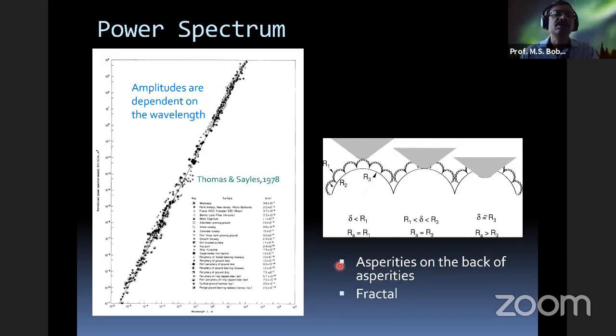So this was the contribution of T.R. Thomas, whose book I was referring to. He found out that by measuring roughness from the roughness of the moon to the smoothest possible surface, if he plots the power spectra function against wavelength, it varies like this. It follows a power law. That is, the asperity height, if it is a fractal, varies as a power law as a function of the radius or the width. As the wavelength becomes smaller and smaller, the height also becomes smaller and smaller. This is the broad gist of the power spectra.